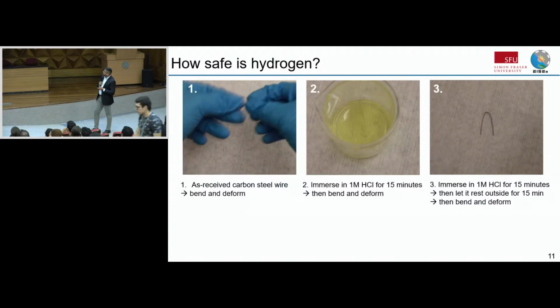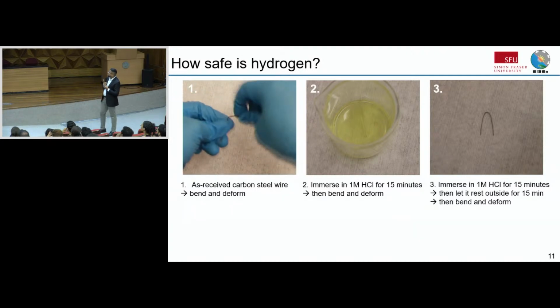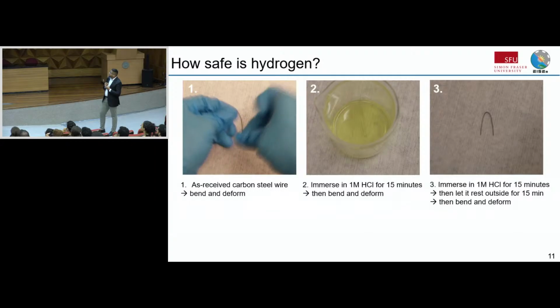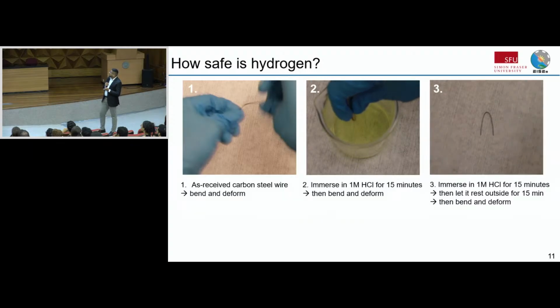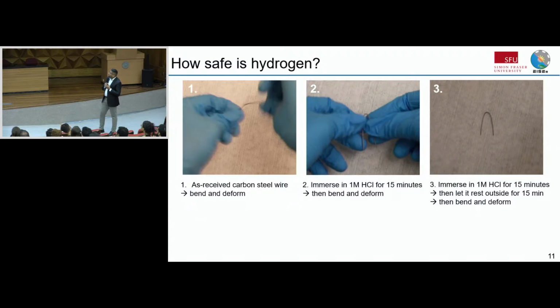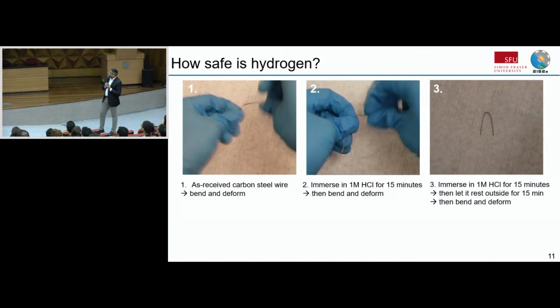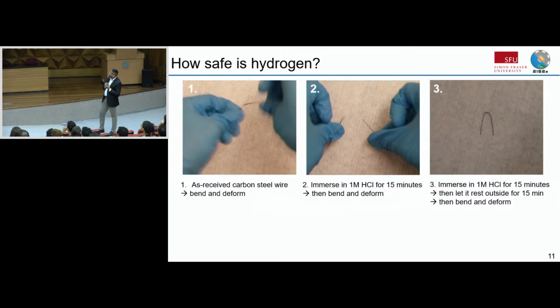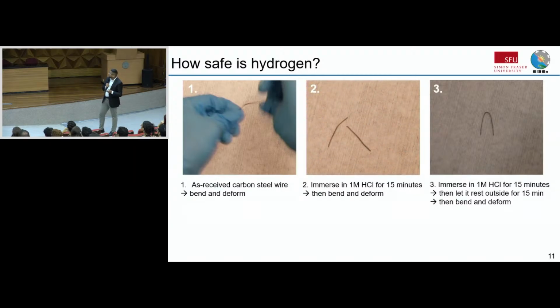So I did this very quick proof of concept experiment with my students, right? When you get a steel wire, if you try to bend and deform it, it doesn't break, and that makes sense because steel has a fairly decent elasticity, right? Now, if you place that same steel wire in hydrochloric acid and let it sit there for 15 minutes, as you saw in that video, there are bubbles evolving because hydrochloric acid is corrosive, right? So then when you do the same thing, you'll see that it breaks, right? And nothing else was done. It was the same wire, you put it in acid for 15 minutes, it's lost its strength.